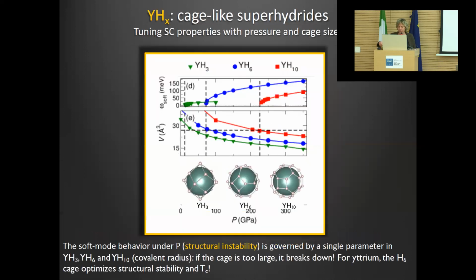One can look at the way that yttrium H10 and yttrium H6 become unstable. What one finds is that there is a phonon mode that drives the system dynamically unstable, which means that the lattice is destroyed. We also found that the pressure at which this instability occurs is determined by the radius of the atom that you put inside. So by playing with atoms with different radii in this kind of cage-like system, one can try to influence at the same time the critical temperature and the range of stability.